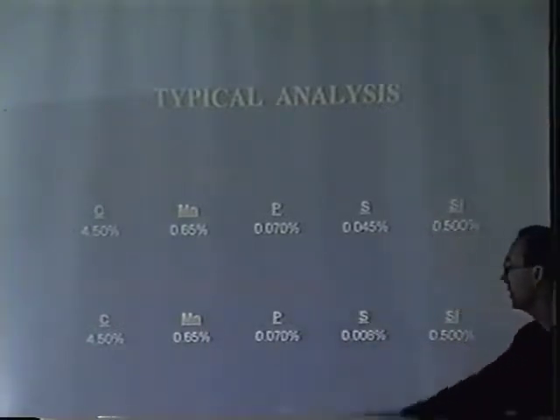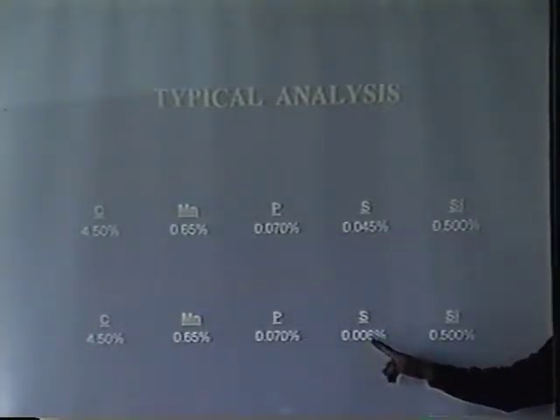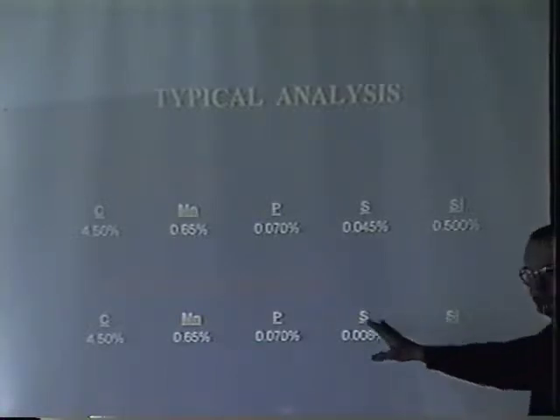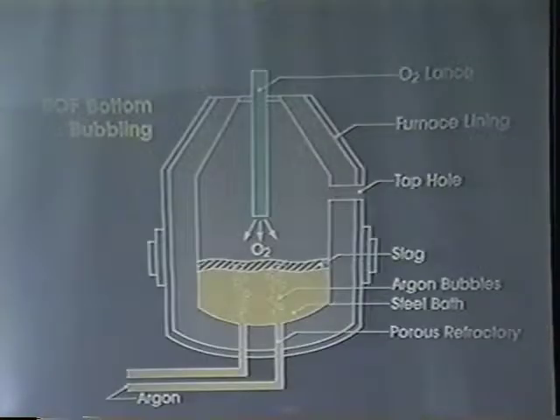And here's the chemistry. Is this showing up? Can we see this? Because here's the chemistry when we're done. We're same carbon level, same manganese, same phos level, but now we've reduced our sulfur level to where we want it for the customer. Most customers are asking for about a 10 max sulfur, which is about a 0.010. I've got a 0.008 here. The best we can do in this shop is a 005 sulfur. We don't do that on a consistent basis, but we do have several customers that are looking for a 5 sulfur, and we can get down there. So now I've got the sulfur out, come along with my crane, I pick the ladle up, and I head for my furnace.